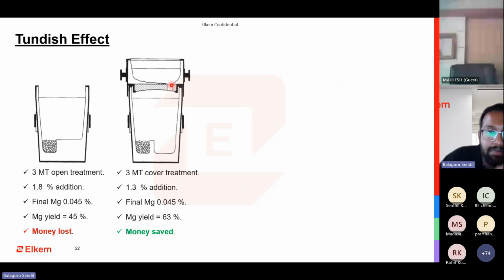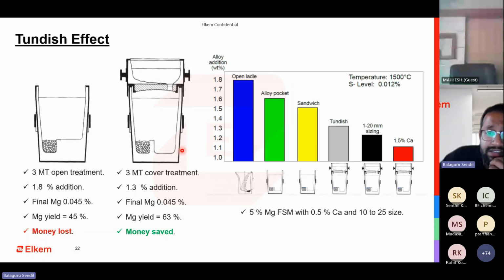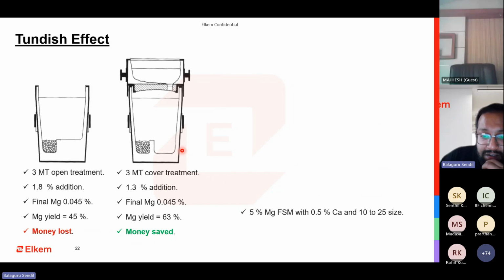We don't make ladles, but we can change the dimensions of it in the correct way so that your ladle movement also doesn't get affected. So this is our typical case study. What we developed in our R&D is that you take a 5% magnesium FSM with 0.5% calcium, and the size range is 10 to 25 mm. This is something that we don't recommend, but this size range is most commonly used, not everywhere, mostly in India.